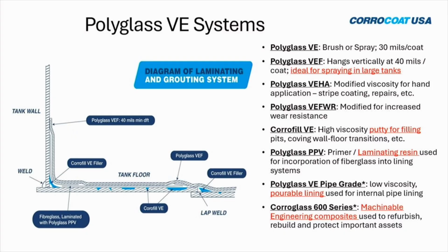So within the VEF and the VE systems, we have primers. We have a standard VE, polyglass VE, which can be spray applied or hand applied. We have the VEF, which hangs at 40 mils. If you're doing a big tank, if it hangs more, it's going to be easier. It's going to cost less. We have the hand applied version. We have a VEFWR that's wear resistant. If you're dealing with slurry or some abrasion resistant, that utilizes silicon carbide and calcined alumina to increase the abrasion resistance.